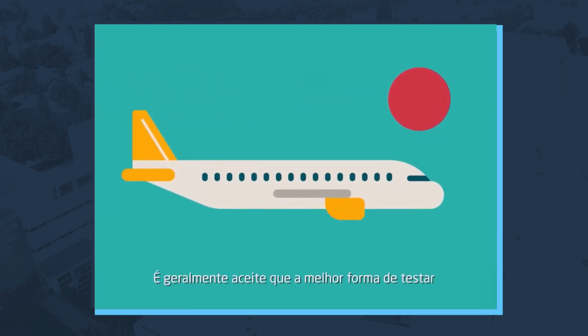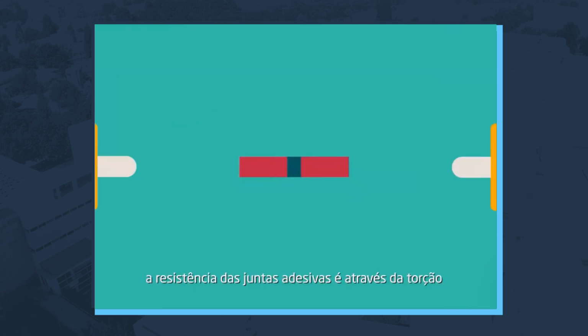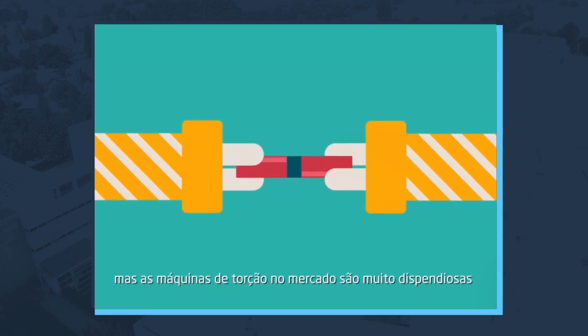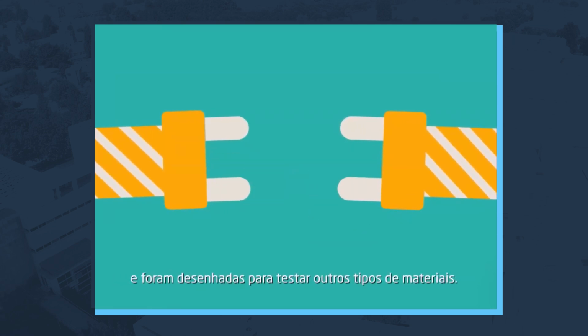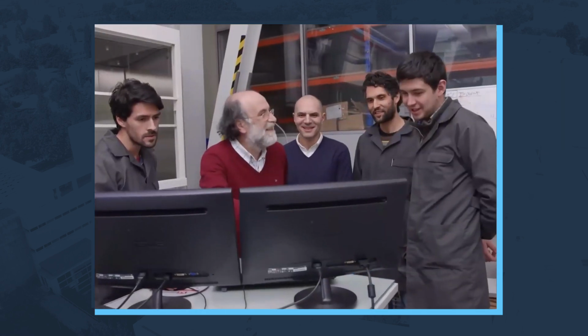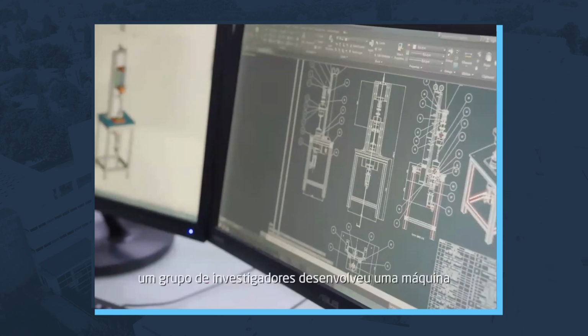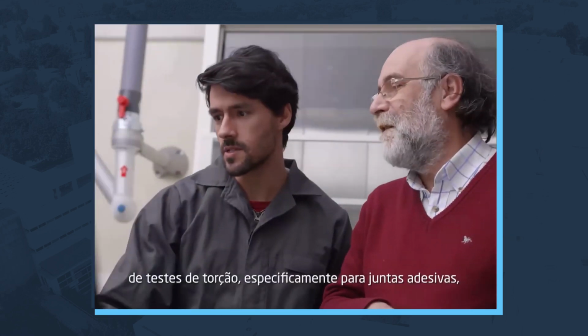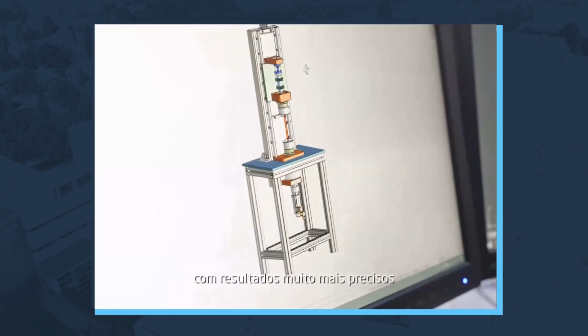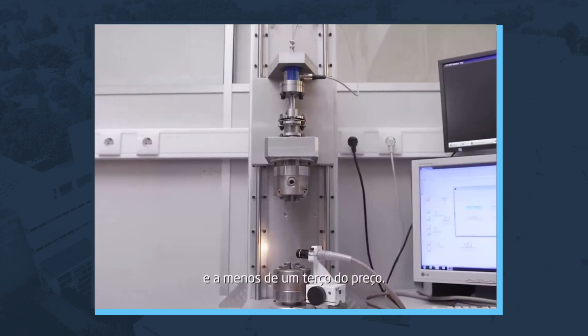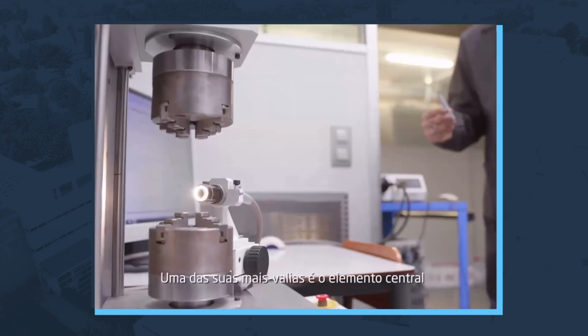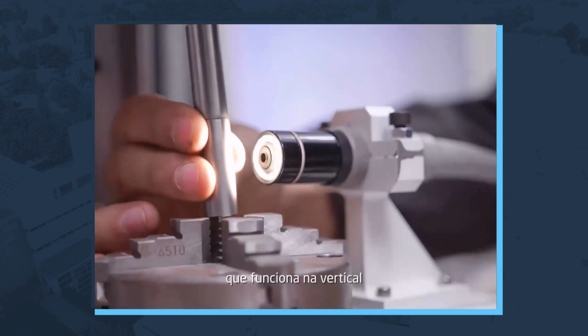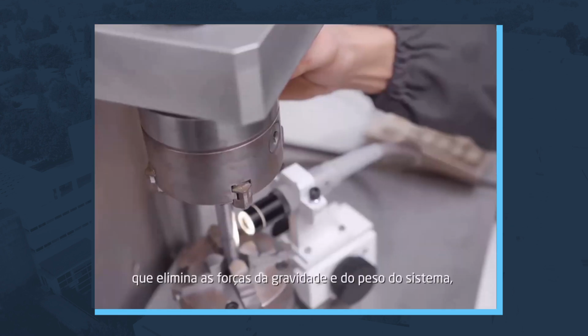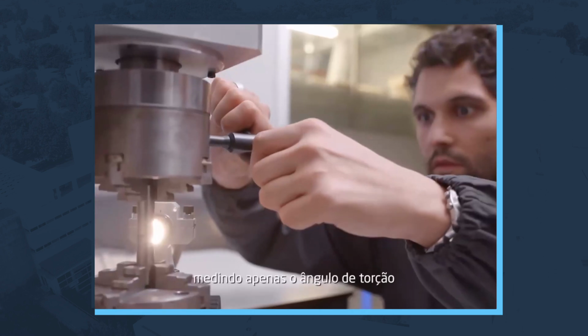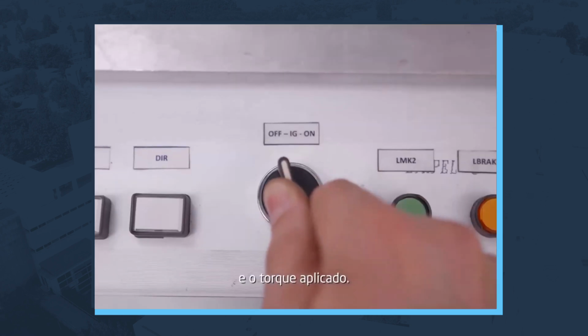It is generally accepted that the stress-strain adhesive properties are better determined under torsion, but current torsion machines are very expensive and were designed to test other types of materials. At the University of Porto, researchers developed a machine for torsion tests specifically for adhesive joints with much more accurate results, and at less than a third of the price. One of the main features is that the center line is in the vertical direction and there's a counterweight to eliminate gravity and weight forces, thus measuring only the torsion angle and torque applied.